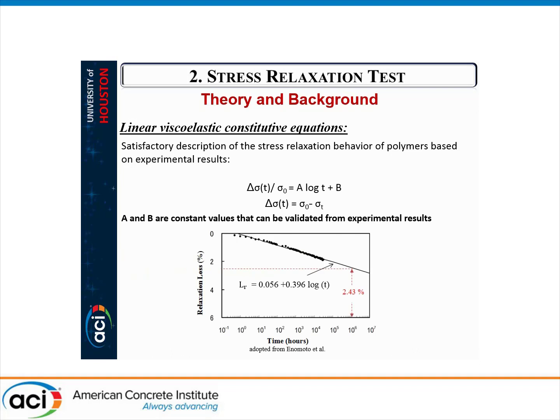As a sample, I have the relaxation result of a CFRP cable with respect to the logarithm of time. As you see, by extrapolation of the best fit line to the experimental result, we can obtain the 1 million hour relaxation, which corresponds to around 100 years, of around 2.43%.